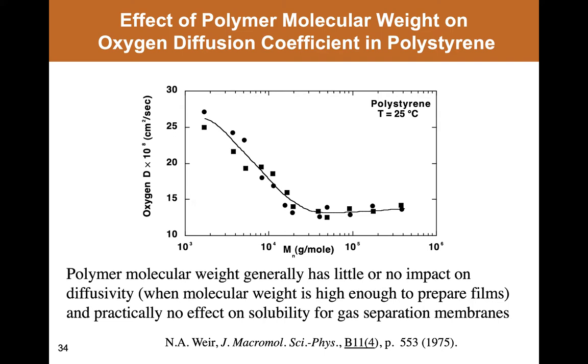parameters in polymers. And if you go to the membrane literature, you'll find that there are many cases where there's essentially no report of the effect of molecular weight on transport properties. There are probably thousands, if not tens of thousands, of papers now in the Journal of Membrane Science where permeation or diffusion properties are reported in polymers, and there's no indication of the molecular weight of the polymer. And while molecular weight can have a profound impact on properties like mechanical properties, viscosity, and so forth, it turns out it has only a small effect on transport properties, and that's why it's often not even reported.